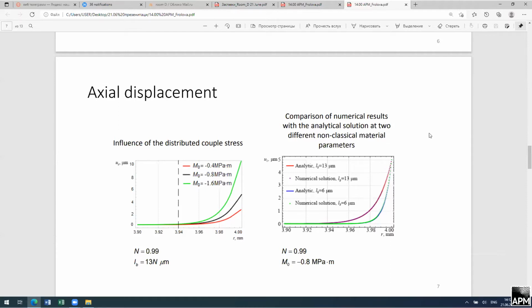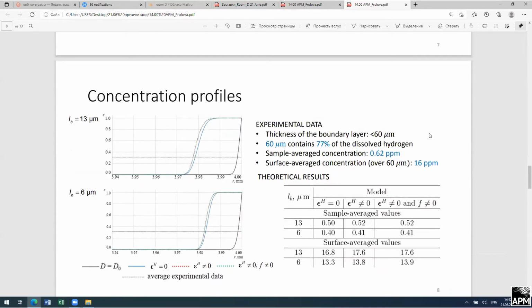On the right plot, you can see comparison of numerical results with analytical solution. You can see that they coincide, and therefore one can use asymptotic assumptions to analyze different dependencies in analytical solution. And also here you can see that using different values of characteristic lengths for bending leads to different thickness of the boundary layer. Here you can see concentration profiles of hydrogen. Black line corresponds to diffusion with constant diffusion coefficients, and other lines correspond to model accounting for dependence of the diffusion coefficient on the elastic strain energy.